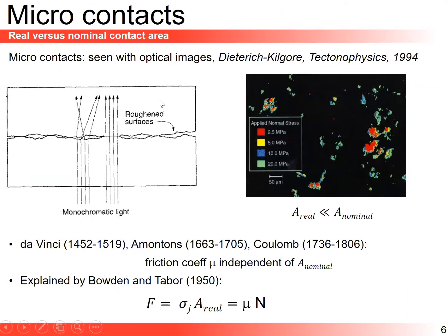And a major consequence of roughness is that you develop microcontacts. Here I'm turning to this classic seminal paper from Dieterich and Kilgore in 1994, where they used transparent blocks so that they could shine a monochromatic light through, and where you establish a microcontact, an intimate contact between the two blocks. At the peaks of the asperities, you can transmit the light, but where you have gaps, the light is diffracted. Therefore, we get direct observations of those microcontacts for varying loads. And those are those bright color spots.